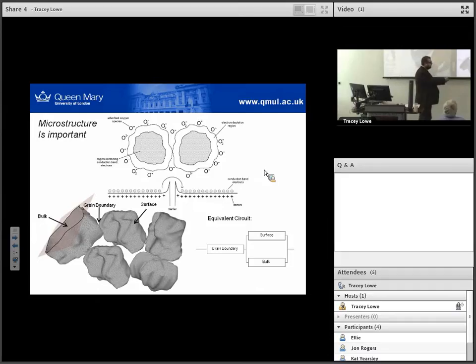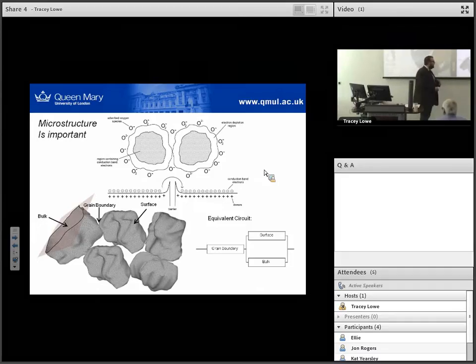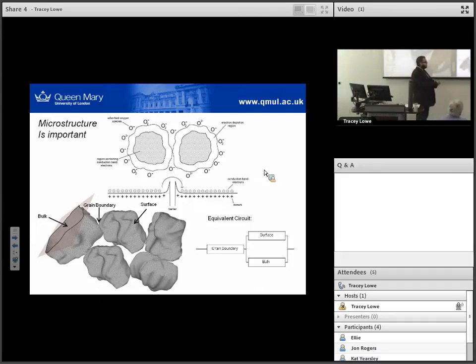You can get an equivalent circuit model, something like this. What we really want to do is maximize the amount of surface that we have so that we can have all of our material being active, so we can get a much bigger response. However, the problem is if we do that, we make these grains smaller, which means we can have a lot more grain boundaries, so our baseline resistance will go up. Just keep that in mind.